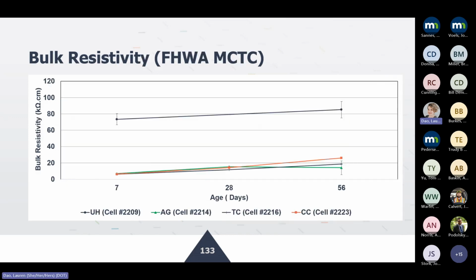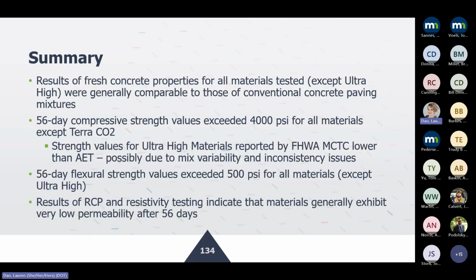And then quickly looking at the bulk resistivity testing, as you would expect with the ultra high, which had very low permeability, you would expect high resistivity. And then in general, it is probably a magnitude of scale away from the other materials. But overall, I would say all these materials would exhibit very, very low permeability. And that should correspond to long-term durability aspects.